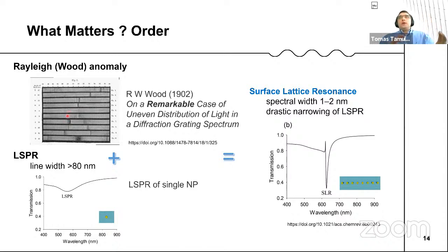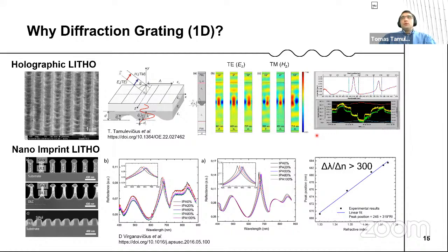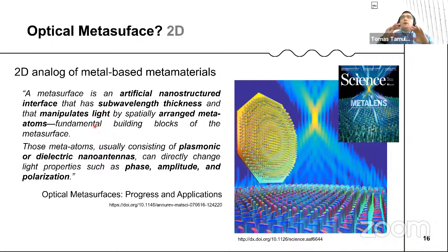And if we put this together with the broad absorption band of the surface plasmon resonance in the nanoparticle, and place those nanoparticles in a special fashion, we have a tremendous narrowing of the LSPR peak, and we can get 1 to 2 nanometer sharp so-called surface lattice resonance peaks, and that was what we were investigating in our work. So it works with dielectric gratings as well, and we had some sinusoidal and rectangular structures. But it's more interesting when you have them not in a line, but in 2D. And then you can call this a metasurface. And I guess you have heard about those as well.